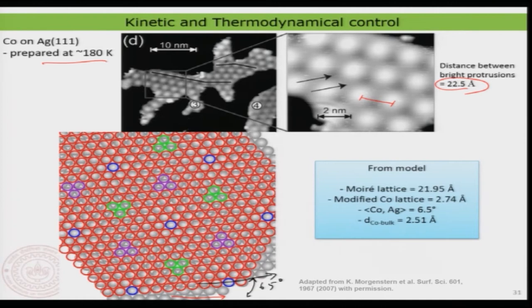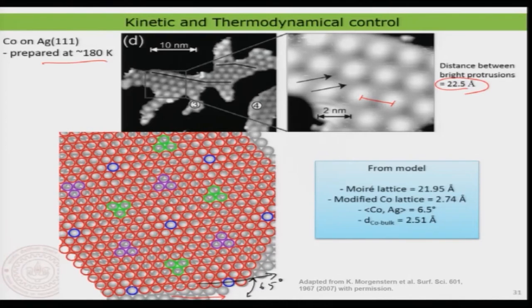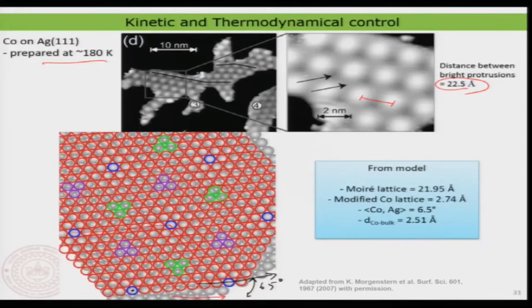Now, when you regenerate the model again, you have to keep in mind the lattices are rotated with respect to each other. Therefore, you would clearly see that the periodicity has to be different. Now, please look at these blue spots. The blue spots are the points where you have a cobalt atom sitting exactly on top of a silver atom. And these spots, the green and the magenta, are where you have the cobalt atom sitting at either an HCP site or an FCC site. With the rotation, it's a bit more complex microscopic structure at the interface. You can now clearly generate the supercell, as I mark here, and that supercell is basically that 22.5 angstrom.